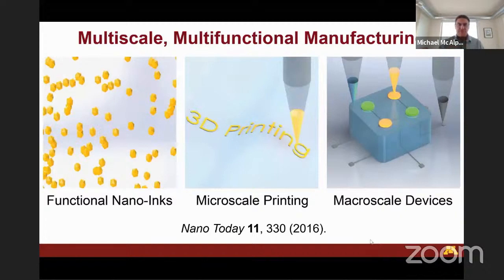And another concept here that we've introduced is this idea that in addition to multifunctionality, in principle, it's also multi-scale. Now, we can't print at the nanoscale because in order to really print something, you have to be able to extrude through a nozzle. And there's only so much shear you can apply before you damage the material or damage the nozzle. But we do use nanoscale inks. So the ink can be at the nanometer scale, especially for incorporating functionality. And then we print at the micron scale, typically 10 to 100 microns or higher. And then we build devices which can be as large as a foot by foot by foot, right? Cubic foot. So we start with our functional nano inks, we print at the micro scale, and then we can develop macro scale devices. So from that sense, it's a multi-scale and multifunctional platform.